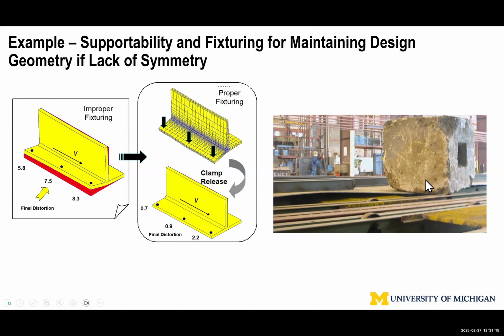And now we see what happened. Remember, we talked about supportability. This bottom doesn't have enough support to give you a reference surface. The base plate, before you put a stiffener on, is reacting to that local big rock loading. This curvature is solely due to the position of this block, producing local elastic deformation. That gets welded into the stiffener, and then we blame the welding process, too much heat input. So actually today, the inaccuracy problem is not just one particular process, it's the entire system lacking process definition.